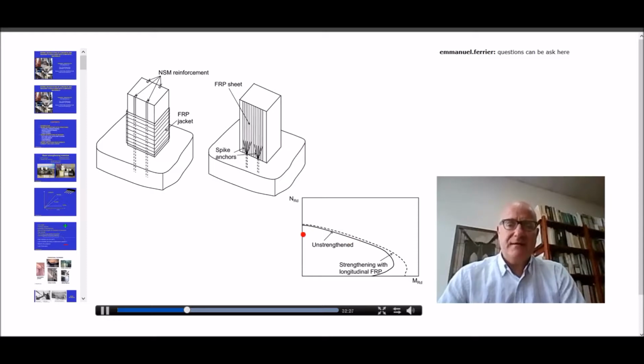It's quite interesting to conclude that if axial forces are high, our external reinforcement is not that beneficial. If they are low, it is quite effective, quite beneficial. That is, it increases the flexural capacity from here to there. So we have an increase in the flexural resistance of our columns only if axial loads are low, which is typically the case in seismic retrofitting. We typically design our structures for low axial loads. So you can see the increase in flexural resistance as a function of the applied axial load.